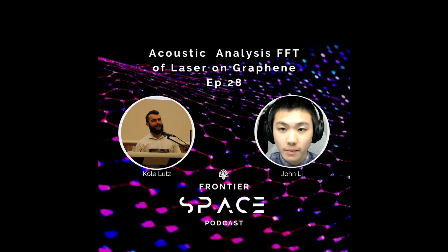As laser-reduced graphene ranges from a porous film all the way up to a fiber attached to the polyimide substrate, depending on what application you're looking for, you want different morphologies and therefore different properties. So here we can basically see, okay, this sound corresponds to this property. It tells us that the sounds contain information regarding what we are forming. And those things that we are forming are either targeted towards a specific application where we are trying to control the morphology, or we are just trying to see what is actually being formed under these conditions. And the sounds can also help us guide or search in that process.